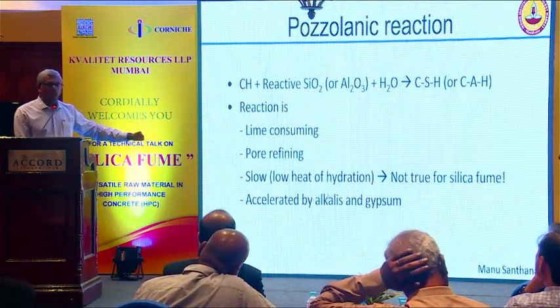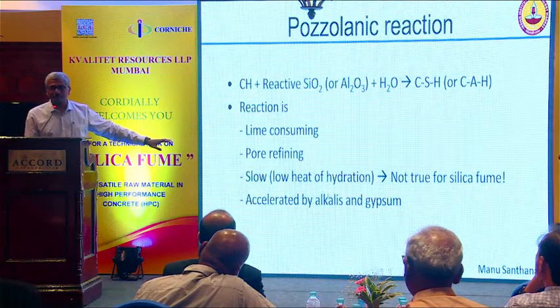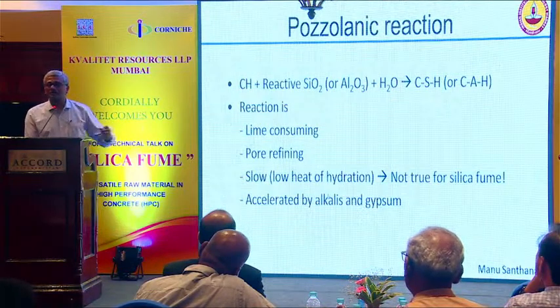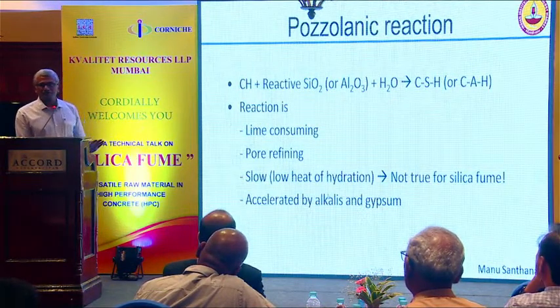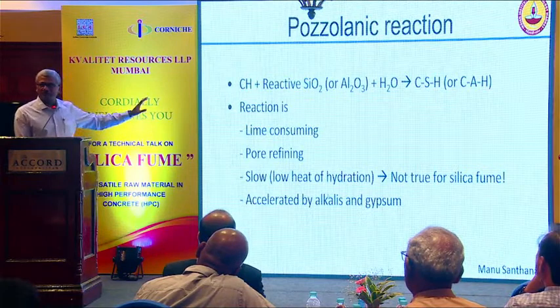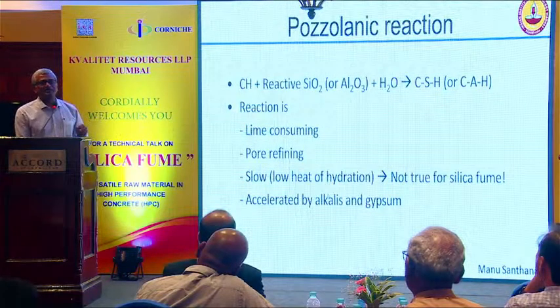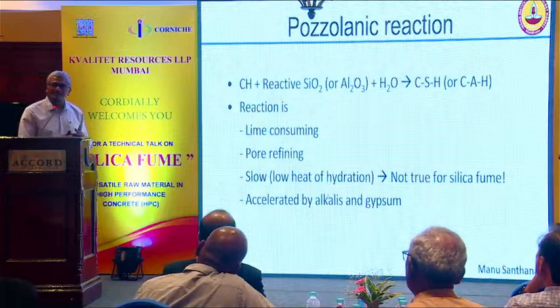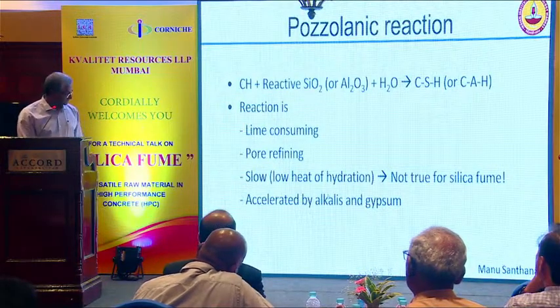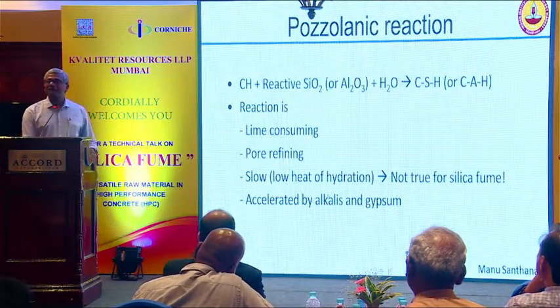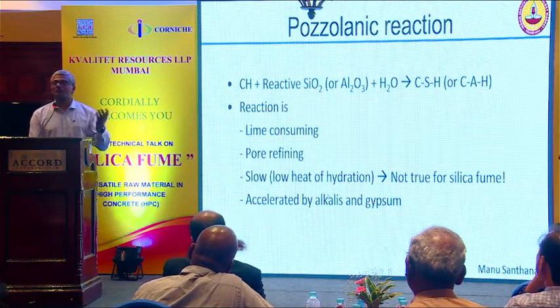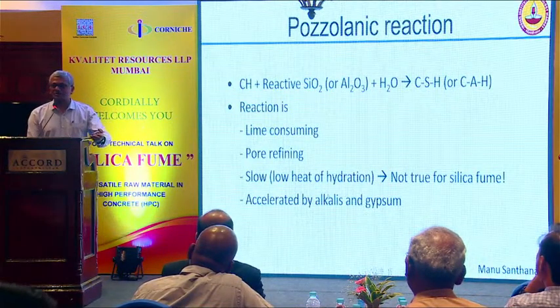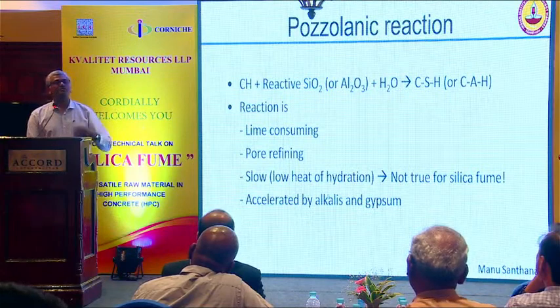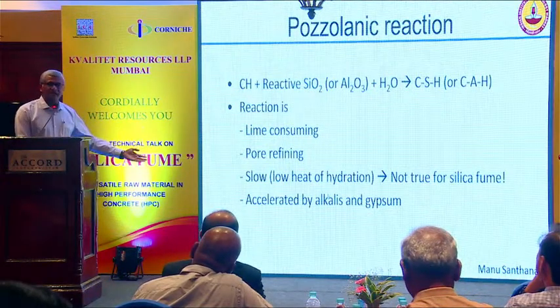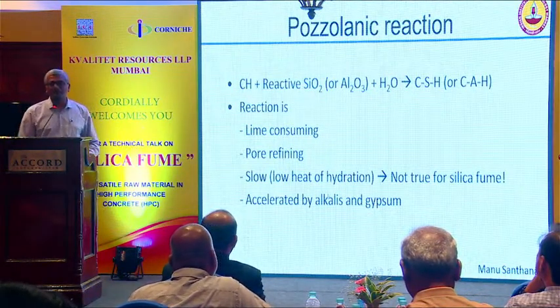So when the reaction is slow, it will lower the heat of hydration. But for high purity metakaolin and for silica fume, that is not necessarily true. This reaction will be fast also because the silica is present in very fine form, so extremely reactive silica is present. And generally when you have alkali or gypsum in the system, like sodium potassium oxide, which is there in your cement, right? And gypsum also is there in the cement, this reaction gets accelerated, so speeded up.